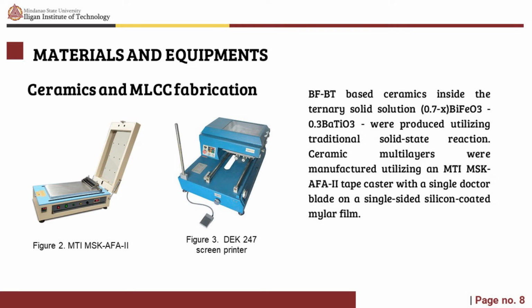Materials and equipment, ceramics and MLCC fabrication. BFBT-based ceramics inside the ternary solid solution of 0.7 bismuth ferrite and 0.3 barium titanate were produced utilizing traditional solid-state reaction. Ceramic multilayers were manufactured utilizing an MTI MSK AFA2 tape caster with a single doctor blade on single-sided silicon-coated Mylar film. The Pt electrodes were printed onto the tape using the DEK 247 screen printer, followed by tape stacking and hot pressing at 70 degrees Celsius for 10 minutes.